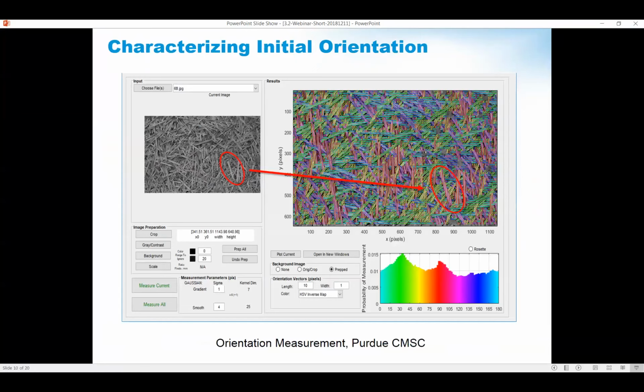Here on the left is an optical photograph of this initial carbon fiber sheet molding compound. You can see the long, almost stick-like looking platelets. We then have passed those through an orientation measurement algorithm that we've developed at Purdue to understand the initial orientation in one of these charges. The colors correspond to the various orientations, and you can see, while not completely uniformly distributed, there are a couple of peaks. Generally speaking, we've got platelets in every given orientation. The key is that we can now take this